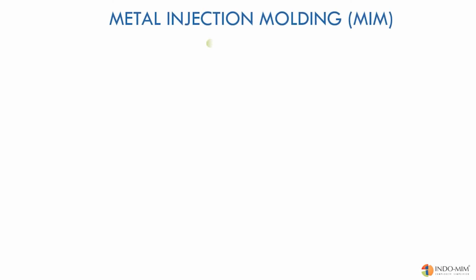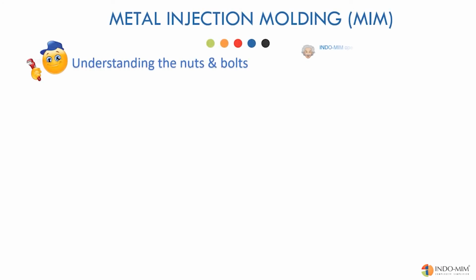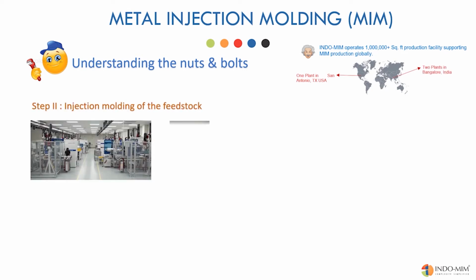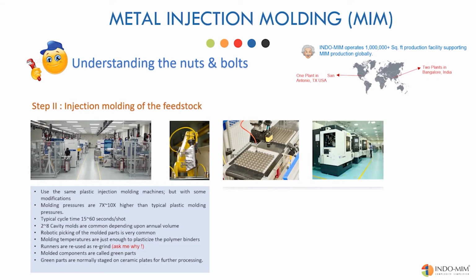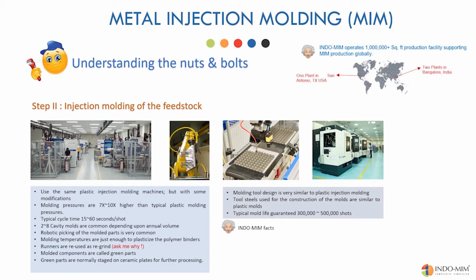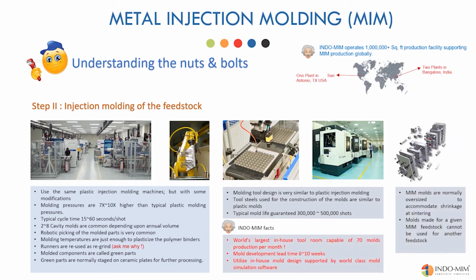Step 2 is injection molding of the feedstock. This process is very similar to plastic injection molding. As a matter of fact, we use the same machines used for plastic injection molding. However, there are some differences. The molding temperatures are just enough to melt the binders added. So, essentially, we are injection molding a semi-solid material.